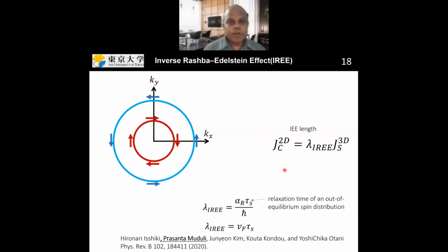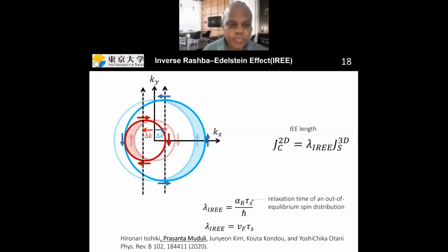Now the reverse process is also true, in which, if you inject a spin current with spin polarization along the y direction, then the Fermi contours will shift like this. The inner contour will shift to the left, and the outer contour will shift to the right. And this will create a 2D charge current, whose magnitude will be given by this expression over here, where lambda is called the Rashba-Edelstein length. You can do a little bit of math, and you can show that this Rashba-Edelstein length is related to the Rashba parameter and a time constant, which is the relaxation time of the out of equilibrium spin distribution.